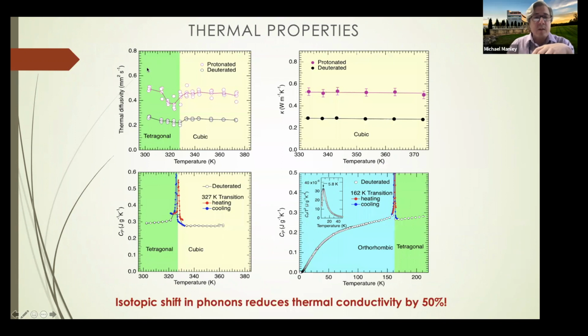And we did additional measurements of the thermal transport. So this is comparing the protonated and deuterated sample. This is what we call the thermal diffusivity, which is looking at the diffusion of temperature in the materials. And you see the thermal diffusivity in the deuterated case is significantly lower than in the protonated case. It's down by about a factor of 2.